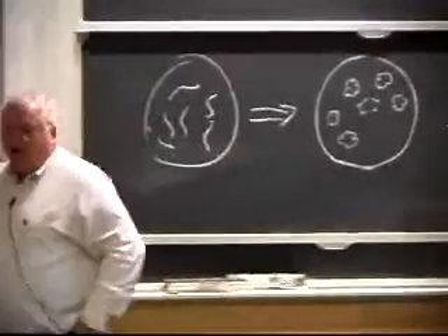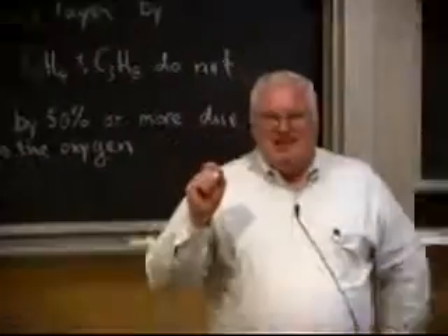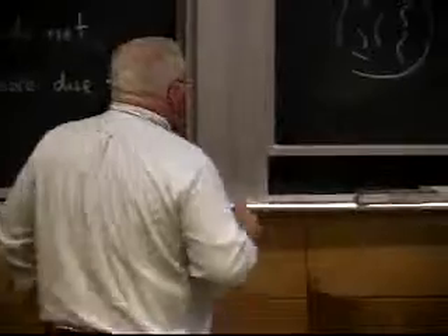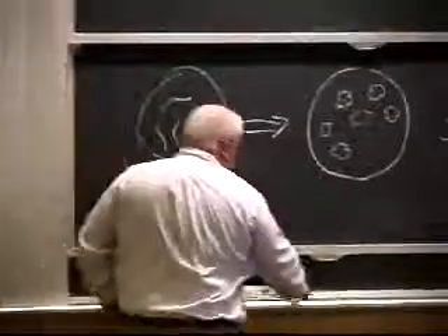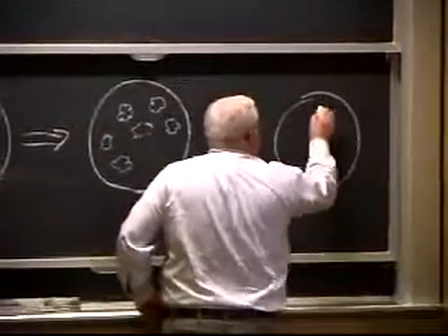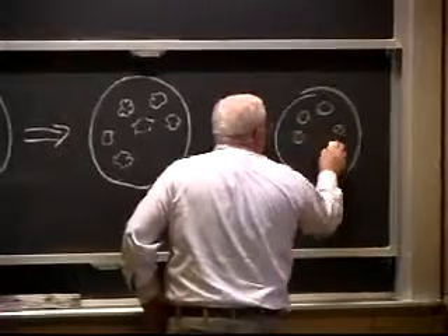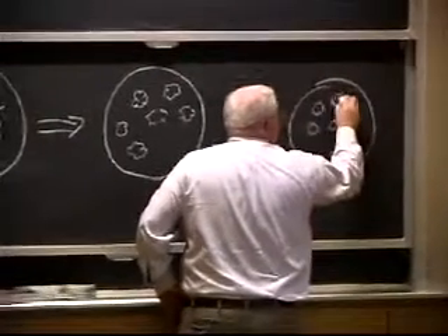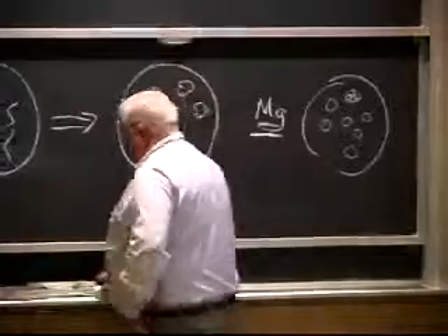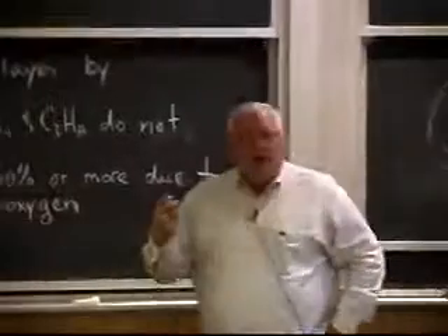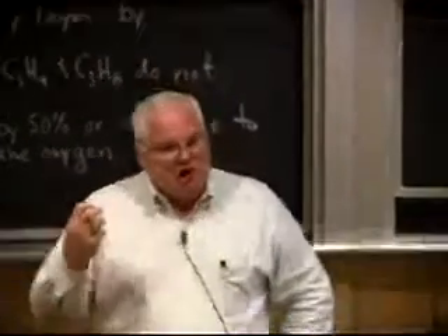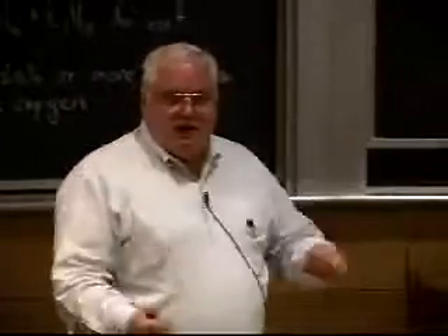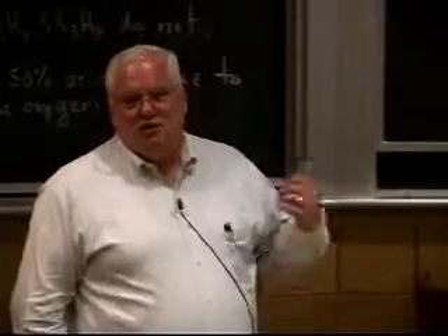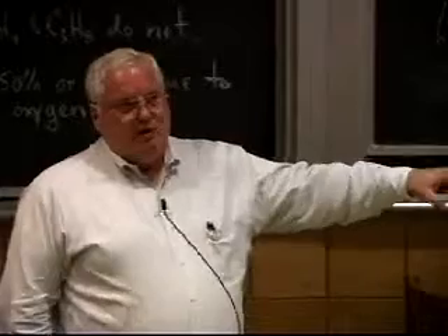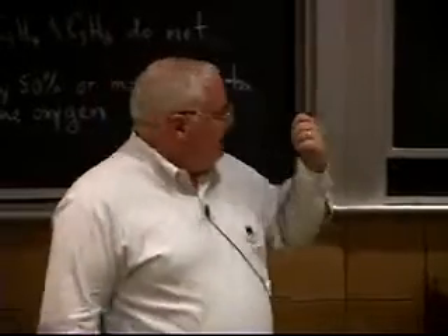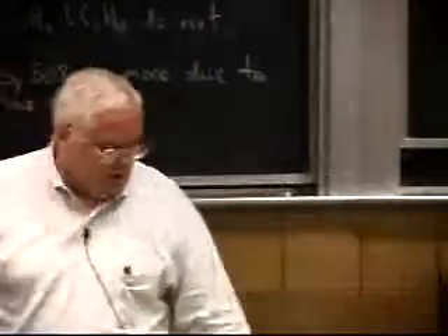Back around mid-century last century, they learned that if you put magnesium into liquid iron, you can actually get the graphite to nucleate spherical instead of flakes. You can get little round things actually called spherulites. The carbon kind of grows in all kinds of little different directions. Sometimes it's called nodular iron. You have little spheres of graphite, and that forms on solidification, and that's called ductile iron. All the cast iron sewer pipe and everything that's made nowadays is nodular iron, or ductile iron.